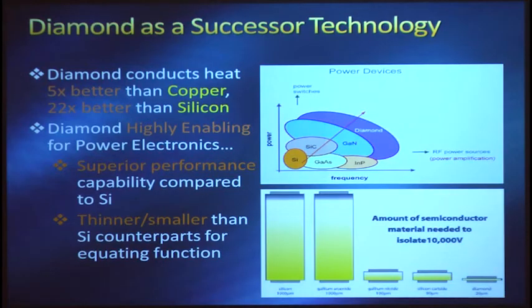So one particular material that's been looked at is diamond as a potential successor technology. And that's because diamond handles heat much better than silicon, about 22 times more efficiently by thermal conductivity, and about 5 times that of copper.